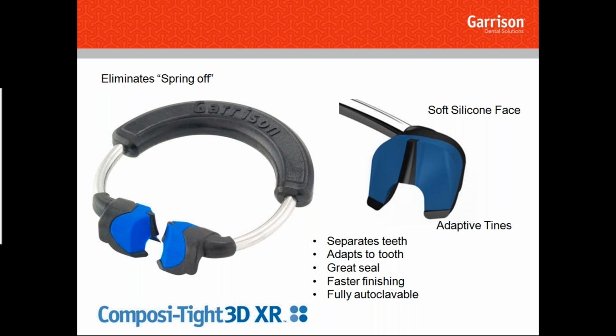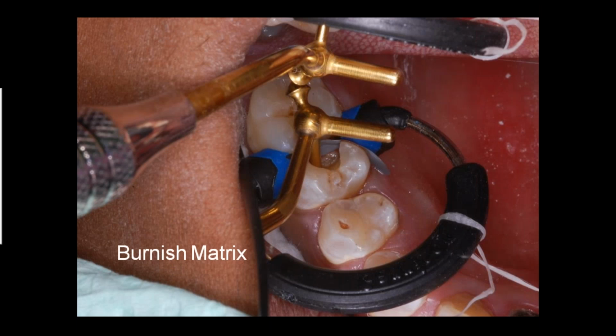And these are easy to place. You use their forceps, and you'll find out they stay on. They don't spring off, or they don't move on because they're so taut. Much better than any of the other ones I've seen on the market. So now we're placing that on. You can see the ring comes from the mesial, obviously for access and removing it on and off, and to eliminate the problems if you were to place it the other way around towards the posterior. But what I'm doing here is burnishing the matrix.